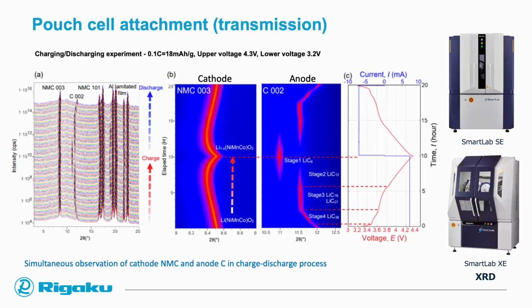What is clearly visible is the shift in the reflex of the cathode material and also the phase change in the anode material. You can see a jump in the carbon due to the phase transformation. From this, we can draw direct conclusions into the battery performance, but it would also be possible to detect other phases which form during the failure of a battery with the help of these attachments. And once again, for this one, you would require a floor standing device, for example, SmartLab SE, but of course also our SmartLab XE system.